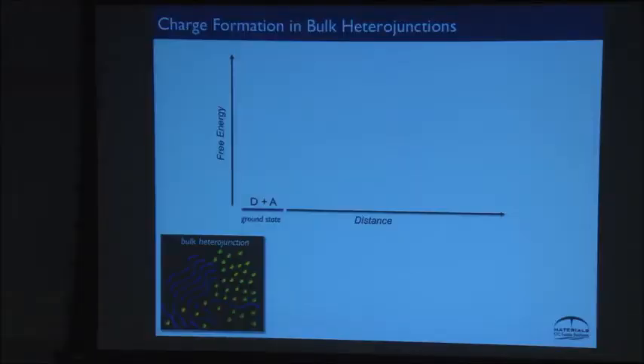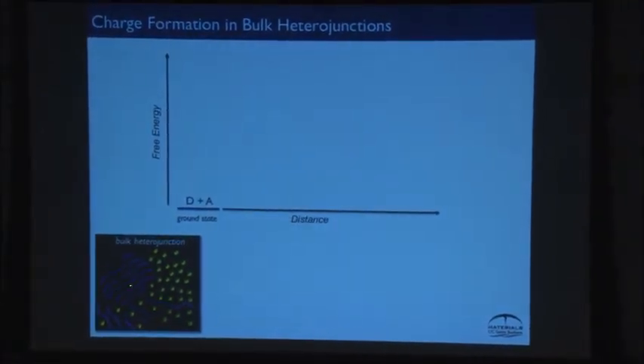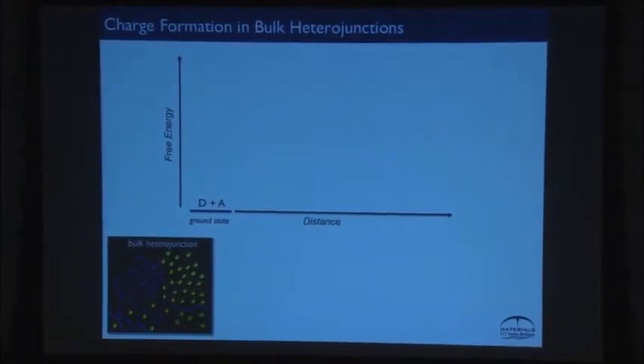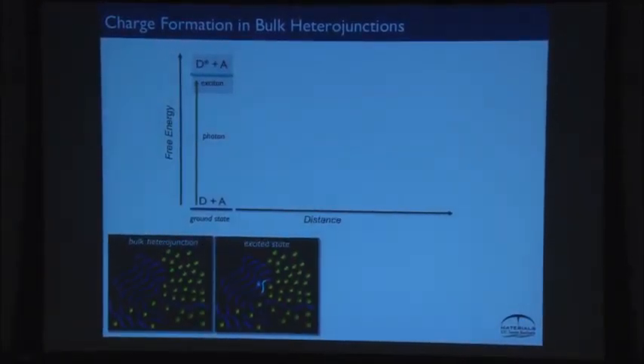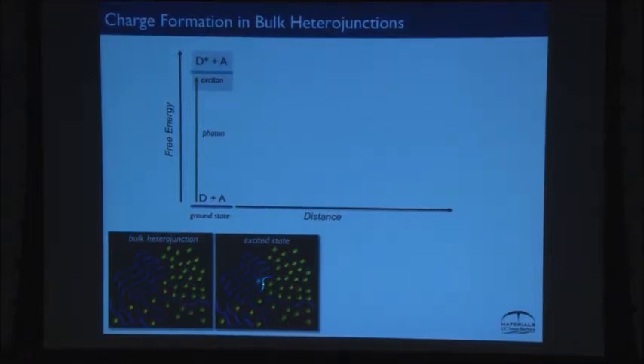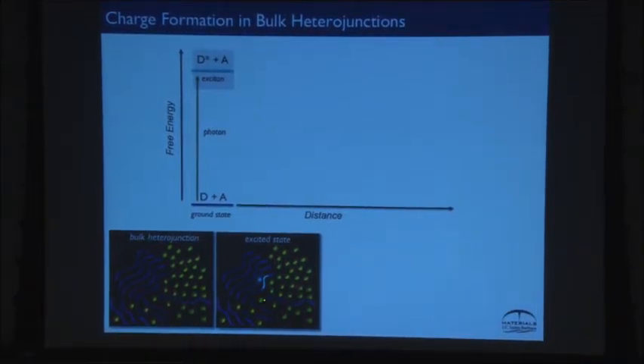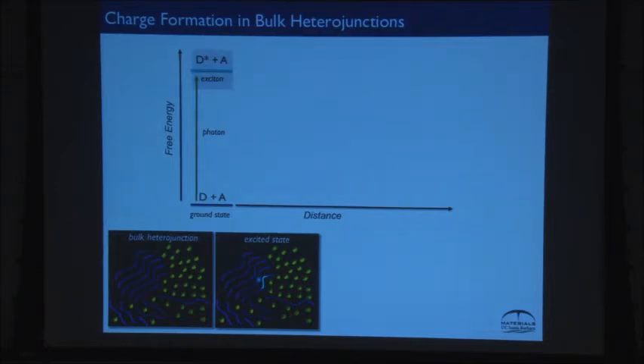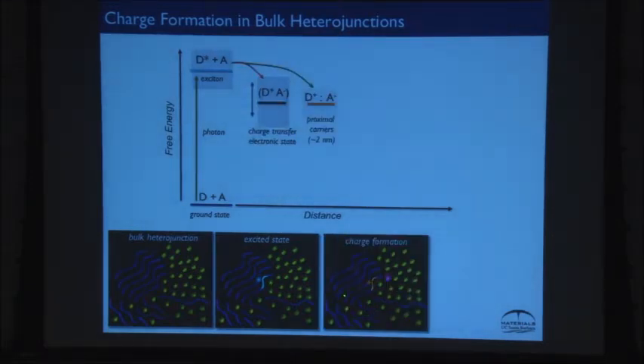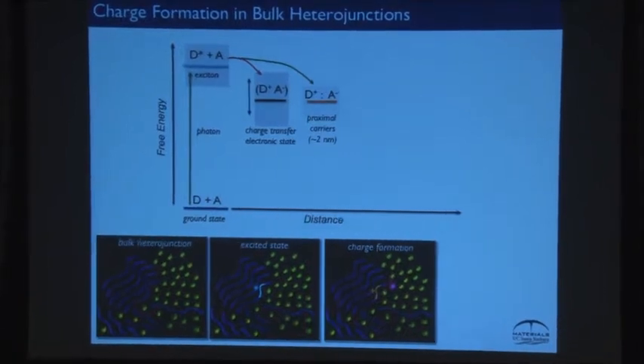Now, to schematically show this, these are drift-based cells, so there's an electric field by the contacts. The idea is this. I have a bulk heterojunction here. These are my polymer chains and my fullerene. What happens is they're in a ground state, and you form an exciton. It's a localized excitation. Maybe it sits on the polymer, and the excitation can walk around. If it finds its way to an interface within its lifetime, it can separate. Basically, you can get a hole and an electron in the two phases. What will happen is this state could be something called a charge transfer state. I draw its energy here because people argue about exactly what energy it has at that interface.